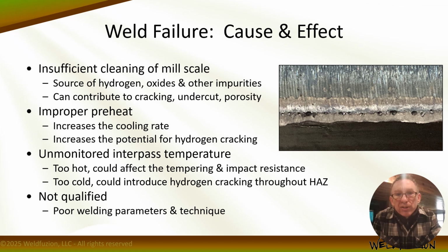Insufficient cleaning of mill scale off the material is more of an issue than you might think. It's a source of trash and garbage that's not good for any weld. Hydrogen, oxides, and other impurities can contribute to cracking, undercut, and porosity. It's just garbage. Insufficient preheat increases the cooling rate and the potential for hydrogen cracking in the heat affected zone.